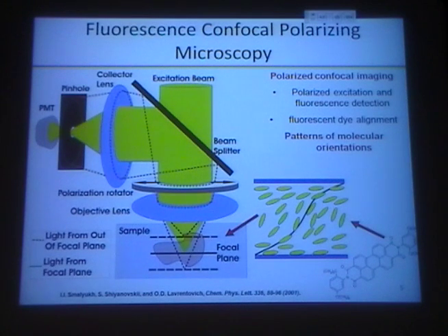So now, because of those two little differences compared to conventional confocal microscopy, we will not only be able to resolve things across the sample thickness, a feature that conventional confocal microscopy already provides, but also the fluorescence signals that we will detect will be orientation sensitive, right? Just because the transition dipole moments of the dichroic or fluorescent dye molecules follow the liquid crystal director, and the intensity of fluorescent light will depend on the angle between the liquid crystal director and the polarization of excitation light, right?